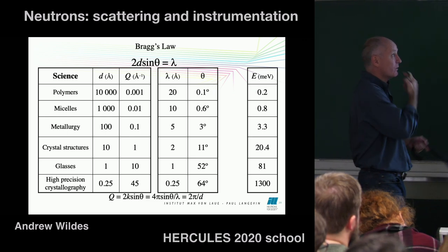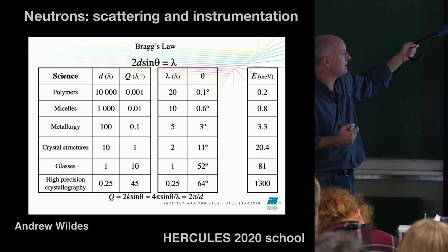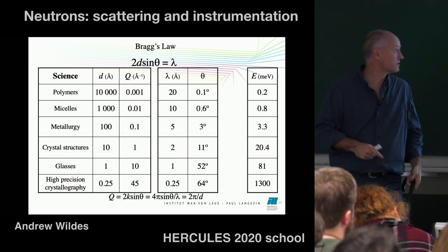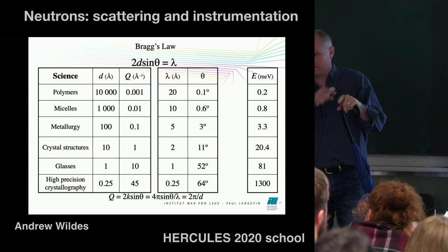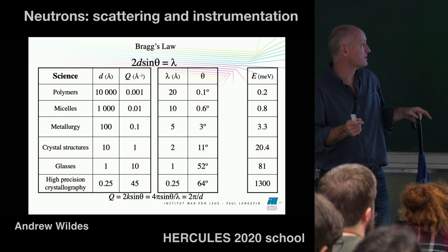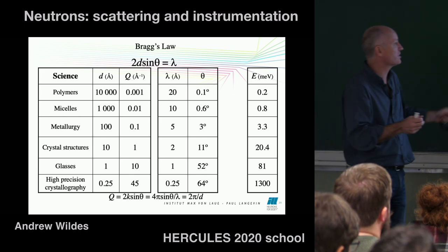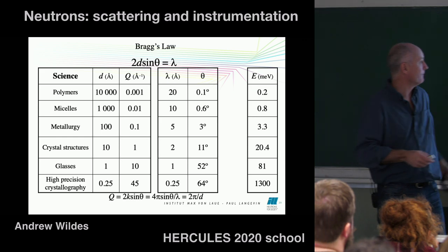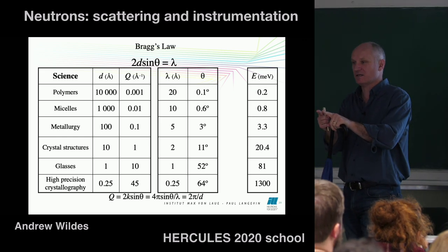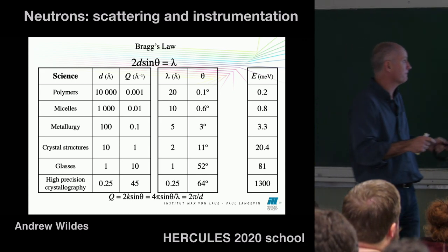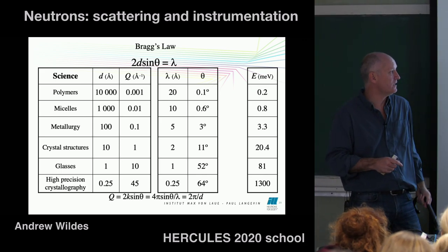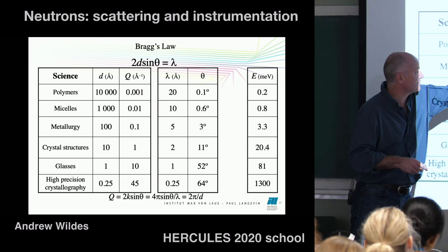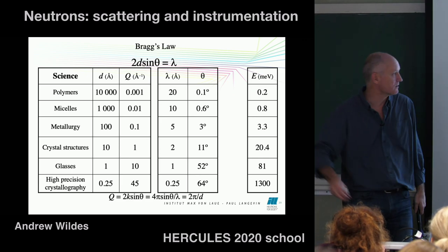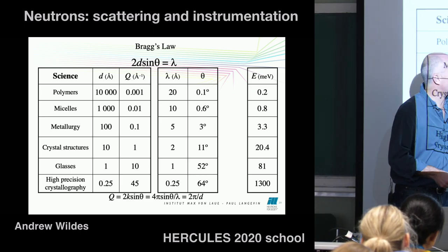So here's a table showing Bragg's law. You've got the different types of science here with the different types of d-spacings that you could access. So polymers, you're looking at something of the order of a micron, I think. Yes. So that's of the order of a micron, 10,000 angstroms. Right down here to glasses or liquids, where you really want to know d-spacings of the order of an angstrom here. You can then look at the momentum transfer that you need to access. You can look at the Bragg angles that you'd need to access to be able to measure those things. And here in the polymers regime, these angles get pretty small. And the energies that equates to for the neutrons vary here over an extremely large range.